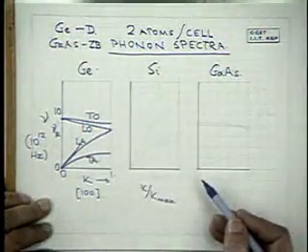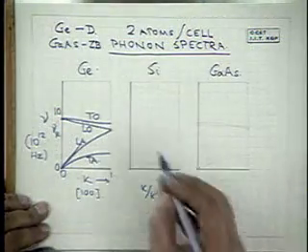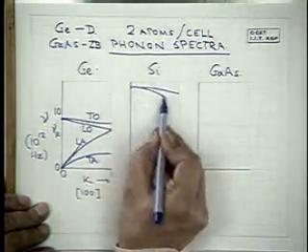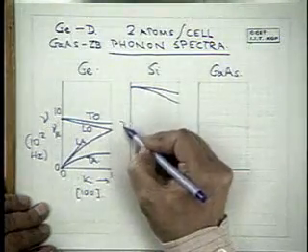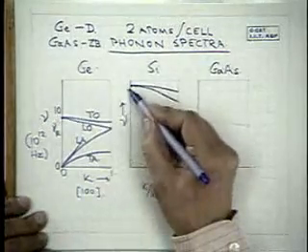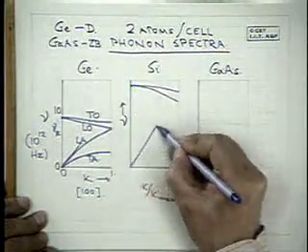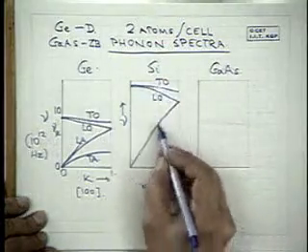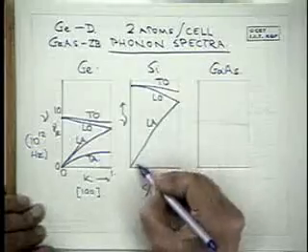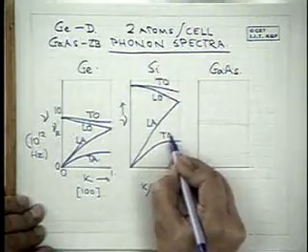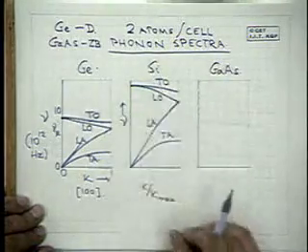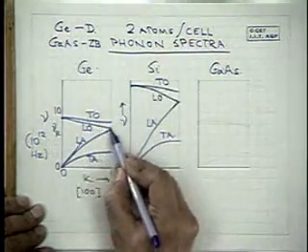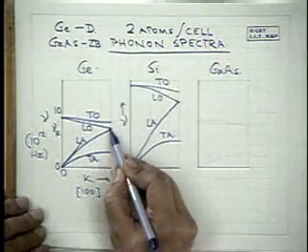Now, silicon, being a much lighter atom, has basically the same type of phonon spectra, but the frequencies are much higher because of lower mass. Otherwise, the nature of the curves is the same, and you notice that in the case of these homopolar, perfectly covalent semiconductors, the LO and the LA phonons are degenerate at the end of the Brillouin zone.